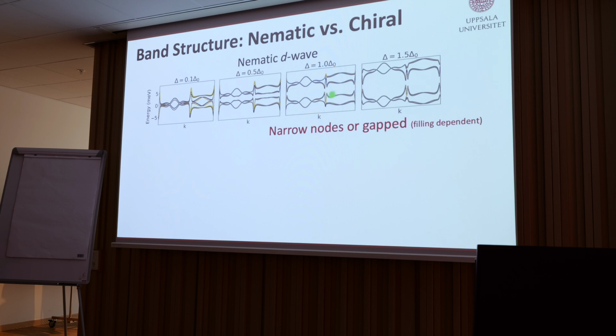There are some sharp features here, and sometimes they go down and truly touch zero energy. It depends on the resolution and whether the nodes are along the high symmetry axis that I plot or not. So often the nematic state has nodal quasi-particles. Sometimes it can miss the zero energy portions, and I actually have a fully gapped spectrum. But often it has some nodal structure.